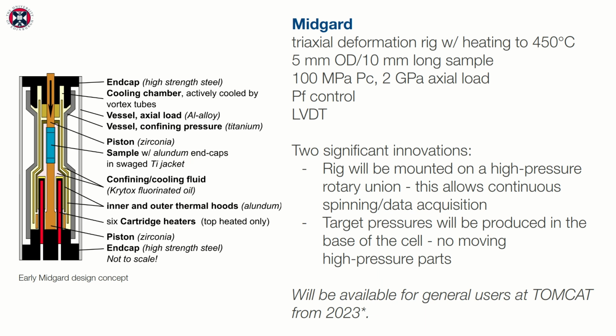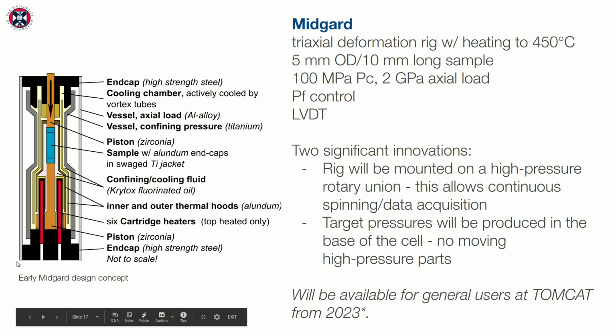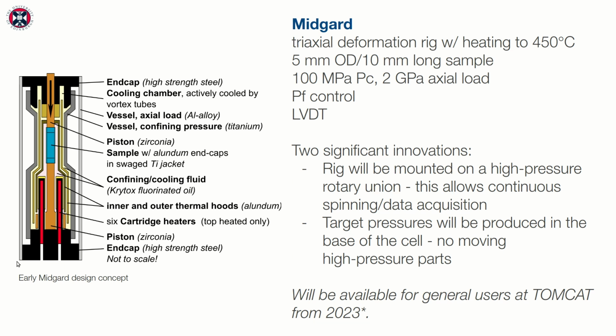Midgard is a game changer for us in a sense, because this is a completely new design, and this is a very early design concept, which I can tell you is not what we will build. We have evolved beyond that, but I can't really show you much of that yet. The key points about Midgard is that it's again a triaxial deformation rig, but it can be heated to 450 degrees Celsius, and it can be pressurized to 100 megapascal confining pressure with a 2 GPa axial load. Again, pore fluid pressure control and an LVDT, which will feed back into the control system.